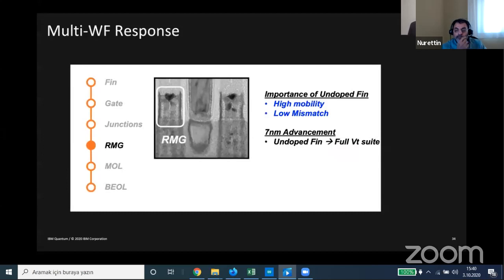Next, we abandoned doping the fin altogether. 14 nanometer was using doping. This resulted in very high mobility in our channel, and it also reduced the mismatch, which is the variations between two adjacent transistors due to random dopant fluctuations.